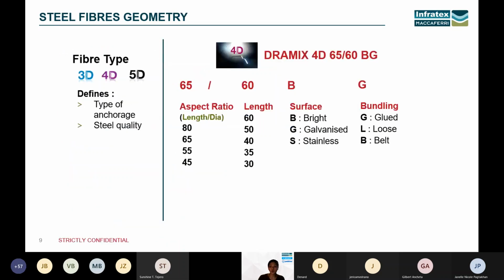Okay, so now go to the geometry of a steel fiber. Okay, so as I've said earlier, we have 3 types, 3D, 4D, and 5D, depending on the type of its anchorage and its quality. So from what we are recommending, it will tell the length over diameter ratio or the aspect ratio or the slenderness. So that is, it can be 80, 65, 55, or 45. So for the length, this is the distance between the outer ends of the fiber. So it can be of 60, 50, 40, 35 mm, or 30 mm.